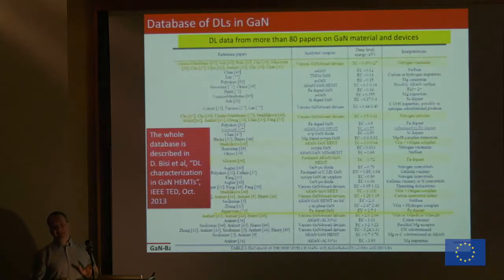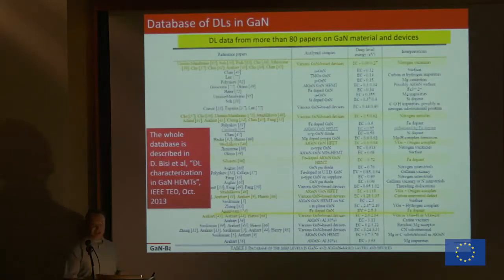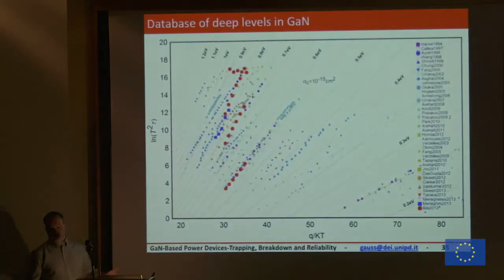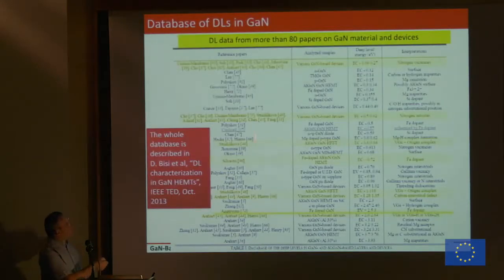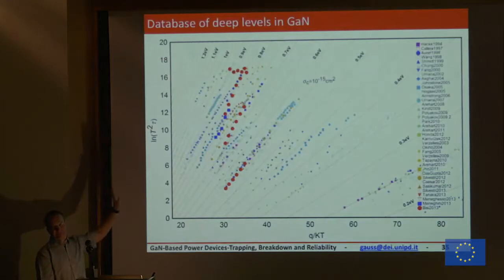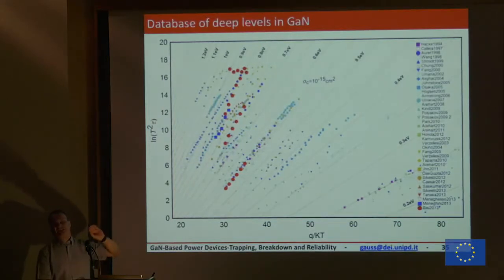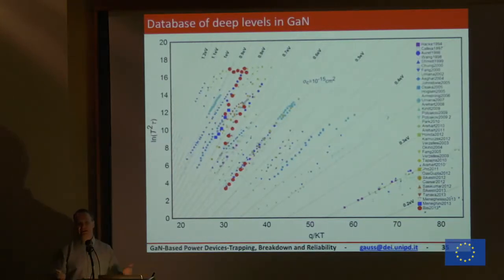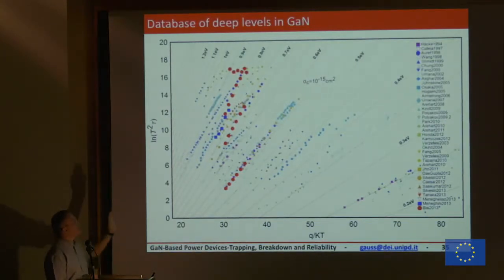Now, let's go back. What can I do when I know the activation energy and cross-section of a trap? First of all, I need a good database. This is an example of a good job done by one of our PhD students, who really went into the literature, took all these papers and all the data points of the traps, and built up this map. These are traps characterized not only in devices, but also in bulk material with several techniques. So nothing to do with the device processing, nothing to do with the device architecture. It is really a map of traps.